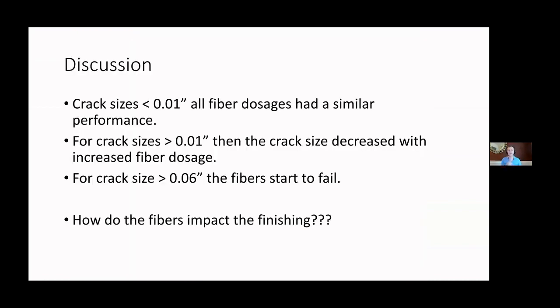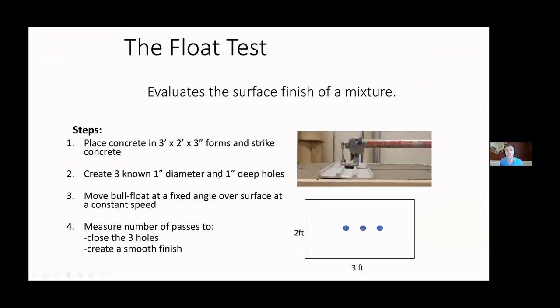So crack size is less than about 0.01. All fiber dosages were about the same. Greater than 0.01, fibers start to do their thing, start to help us. And for larger crack sizes, fibers start to fail. But I know what you're asking out there, because I was. How do these fibers impact the finishing of our concrete? Oh, well, we got another test for you called the float test.